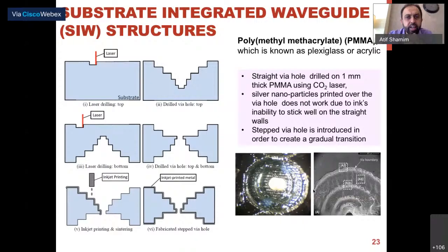We actually created a staircase on both sides. If you could see in this figure, we have staircases. This is created through laser from one side, and then the staircase on the other side. And then we printed, and that actually worked because on the horizontal layers, the ink was able to stay. And with just five layers of printing, we got decent vias. You could see some pictures on the right side.